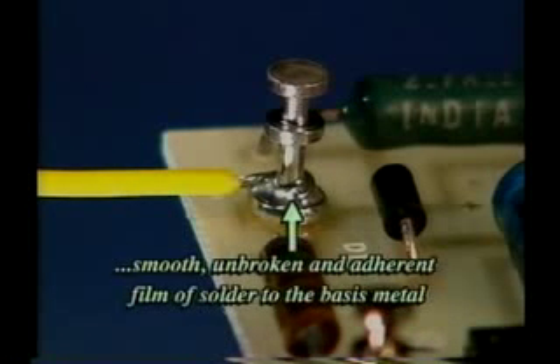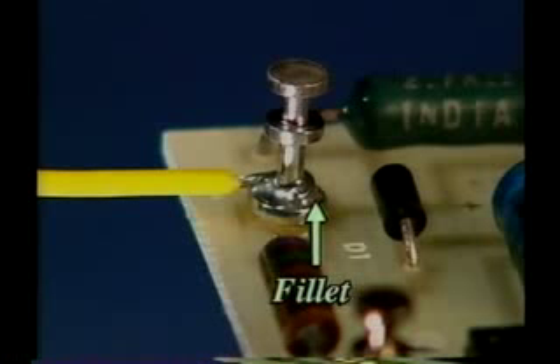Once the flux is cleaned, we check that the solder is feathered out smoothly, showing good wetting action over all elements of the joint. Wetting is the formation of a smooth, unbroken, and adherent film of solder to the base metal. This area is called a fillet. On a proper solder joint, the solder fillet is slightly concave or curved inwards.